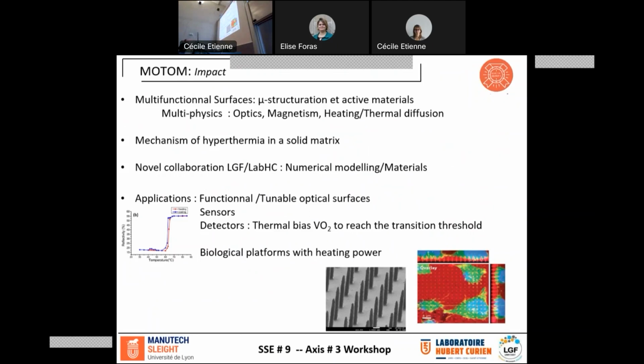In terms of application, what are the targets? As I have just shown in the beginning, this is to realize functional or tunable optical surfaces. We can also think about sensors, for example, magnetic sensors, but also optical detectors, which are based on vanadium dioxide. But in that situation, when this material is supposed to be used in an optical detector, the threshold transition is quite high in order that the photons can induce the transition of the material. So the idea can be, for example, to use magnetic effect to increase a bit the temperature and to be much closer to the threshold, in order that after, photons can induce the transition.